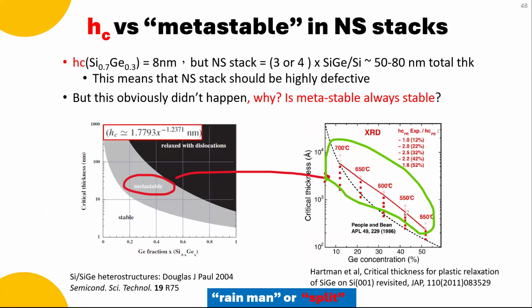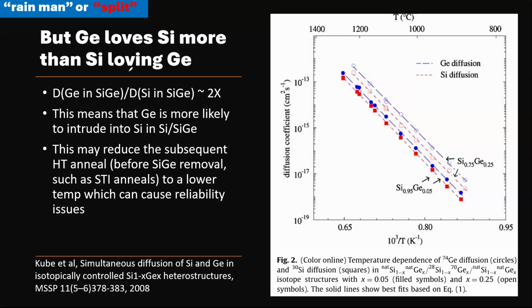And that 1 nanometer could hurt you because of what? The thermal diffusion. Germanium loves silicon more than silicon loving germanium. Germanium likes to go into silicon, but not the other way around. It's 2x. The diffusion coefficient change is like 2x. Look at this curve. The blue line is always more than 2x of the silicon line with different germanium concentration. The higher germanium concentration, the worse. 25% is 2x. I mean, if you're 30%, it's much higher. So this is like that. What does that mean? That means that once you form, initially you may be perfect, no diffusion, but later on you will see it.